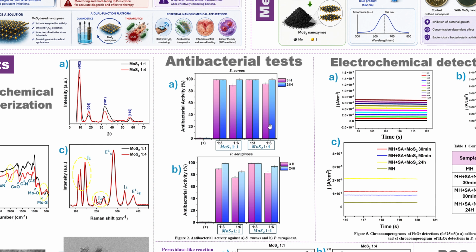In the next part, we evaluate whether this catalytic behavior could be associated with the antibacterial activity. The nanozymes were tested against Staphylococcus aureus and Pseudomonas aeruginosa using controlled hydrogen peroxide conditions. As shown in the graphs, both molybdenum disulfide formulations exhibit significant antibacterial activity. For Staphylococcus aureus, the treatments produced very high antibacterial activity after both 3 and 24 hours. A similar behavior was observed for Pseudomonas aeruginosa, although some differences between the formulations and concentrations were observed.